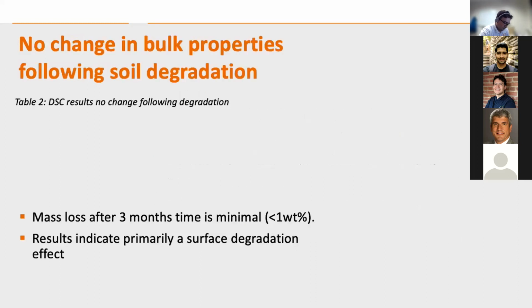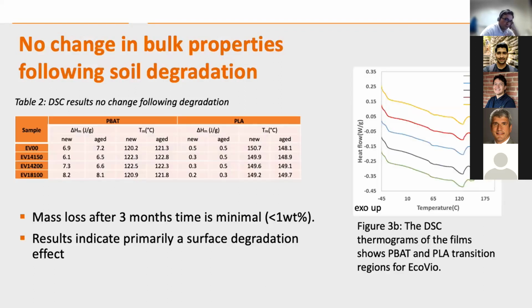First, we wanted to confirm any changes in the bulk properties of these films because we never wanted any changes in the bulk properties of these films, because changing bulk properties would also result in changing how it degrades, such as the mechanism, and also it could mean changes in its mechanical properties. We did thermal analysis using a DSC, which shows the melting transitions in figure 3a, and table 2 along with figure 3b shows no change in the melting point of the films even after treatment and even after they were placed in soil.